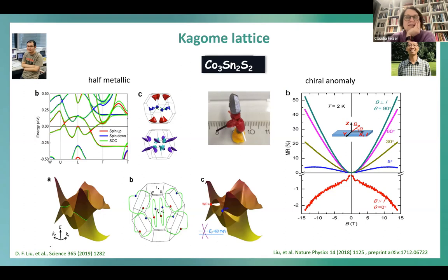And we also showed the chiral anomaly here because the referee wants to see this, so we said, okay, we do it. But in a magnetic system, I would say one should be more careful because negative magnetoresistance is not a rare case in magnetic systems. Anyway, this was the starting point.